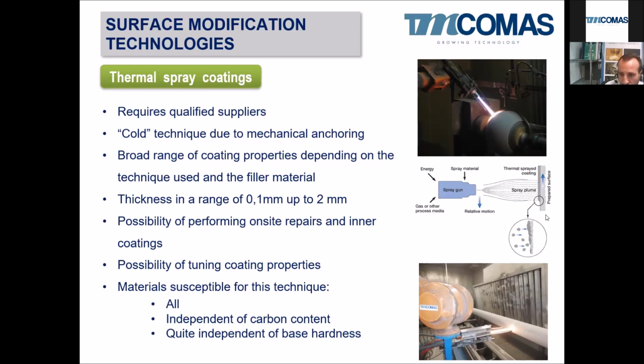Okay, let's continue. So yes, at the end there are a lot of particles that are going to be deposited onto this surface. It's like painting, but with metallic or ceramic particles. So it's a cold technique. Why do we call it cold? Because there's no diffusion, no welding, no fusion of the base material. The fusion takes place in the gun, but not on the surface. So the heat input to the part itself is quite low. That allows us to apply extremely hard coatings on very slim parts like this compressor shaft.